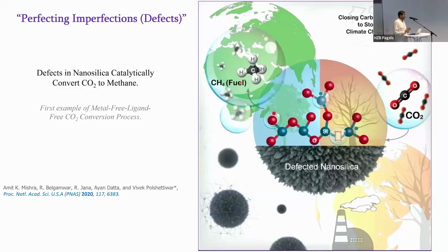And then we came up with the idea of creating defects in the material. So silica is nothing but Si-O, Si-O, Si-O, right? It is an amorphous siloxane network. So we broke this Si-O bond. If you break the bond, then you get an oxygen radical, you get an Si radical, you also get oxygen vacancies, right? And so we asked two questions: how do we generate these radicals, and whether these radicals and oxygen vacancies can activate the CO2 and dissociate the hydrogen.